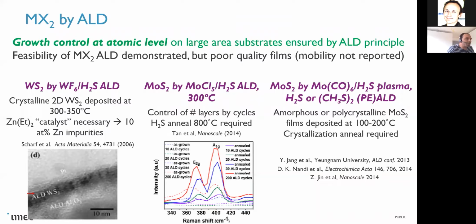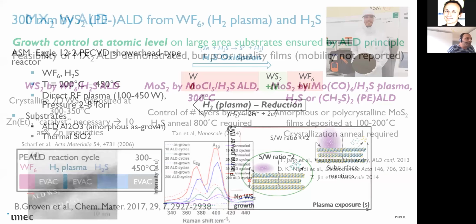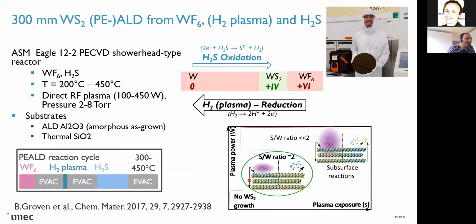This is just to show that we started basically to work 6 years ago on ALD methods. And we could understand relatively well our process, for which we needed to go to a plasma enhanced ALD to tune the oxidation level of the tungsten. We are trying to grow tungsten disulfide, and the reactor that we were using was a 200 degree to 450 degree direct RF plasma reactor.